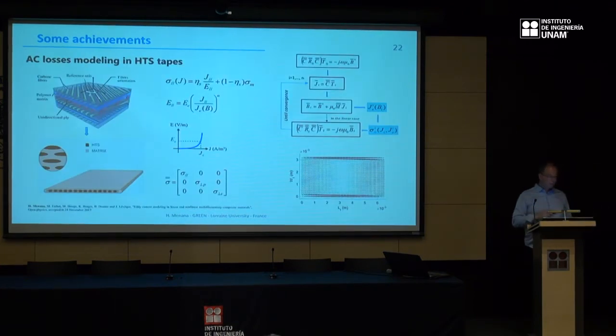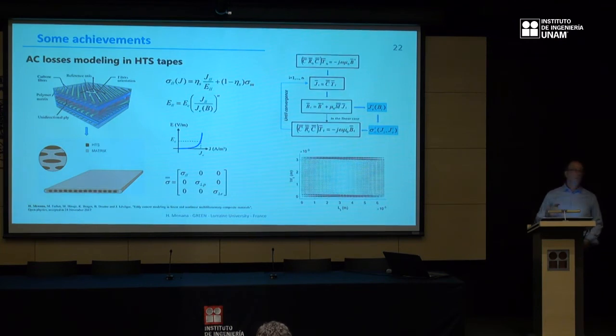This type of modeling has been adapted to model composite superconductive materials, composite tapes, which are constituted of high temperature superconductive material embedded in a conductive matrix. The structure of these composite tapes is similar to the CFRP, so we used the same approach to model such materials, including the same iterative approach for solving the matrix equation with an update. Since the system is nonlinear, we update the value of the critical current that depends on the magnetic field, and the conductivity that depends on the critical current.